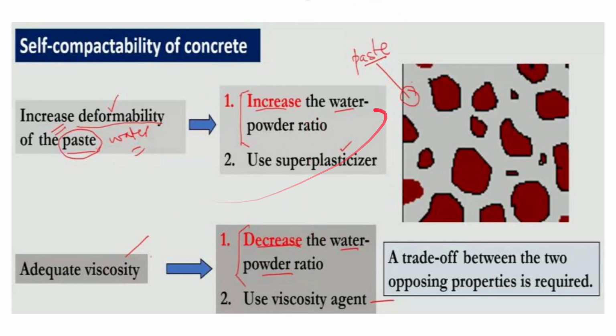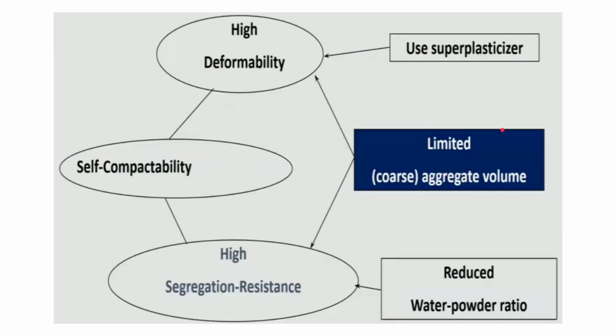Therefore we need to find an optimum, balanced value as per our requirements. As you can see in this flow chart, high deformability can be achieved by using superplasticizer, and high segregation resistance by a reduced water powder ratio, but both are opposite. To achieve self compactability we need both. Apart from that, these can also be achieved by using limited coarse aggregate volume. That's why the coarse aggregate concentration is quite low in SCC.